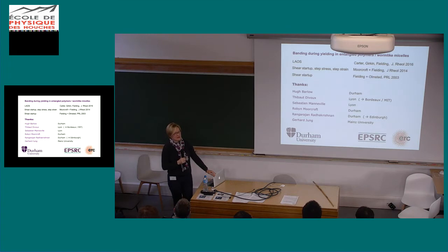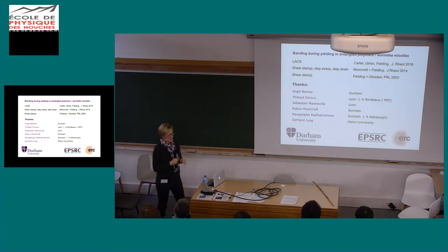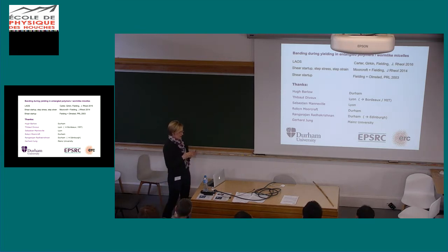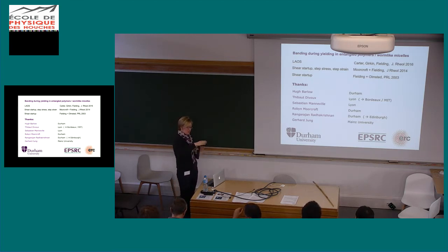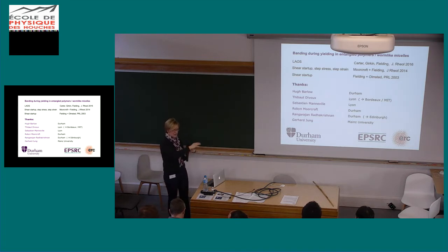Yeah, right. So I think that's something that's seen a bit differently in the rheology community, maybe as compared to more the statistical physics community. So the rheology community, I think, generally are motivated by how experiments are done actually in rheometers. And okay, this sketch that we draw of planar shear is, you know, that's a theorist's cartoon, and the rheometer will always in practice have some curvature to it, which means that there's some heterogeneity forced by the rheometer because the stress is larger near the inner cylinder than the outer cylinder. The same is also true in cone and plate, but a bit more complicated.